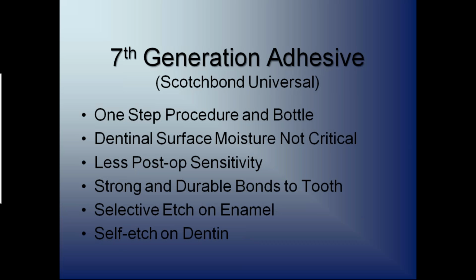And this we're going to talk about our 7th generation adhesive. And I use Scotch Bond Universal. It's the #1 selling adhesive from 3M Oral Care in North America. You look study after study in how predictable it is. It's a one bottle, one application. The adhesive, we don't have to mix a primer and adhesive together. The dental surface moisture is not critical. Post-operative sensitivity is eliminated. And it bonds to dentin 25-30 megapascals.